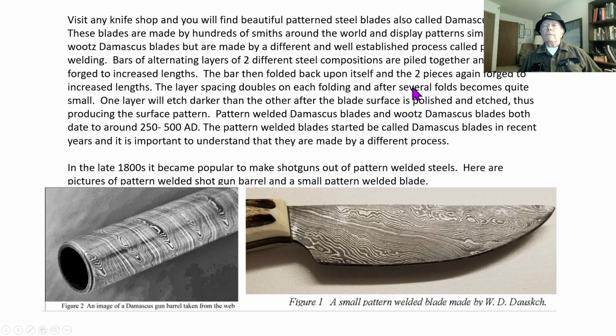So it doesn't take long. After several folds, you get a lot of layers. Now, because of different compositions, one lights up dark and the other lights up white on the surface. And this gives you the pattern that you can see with your eyeball.